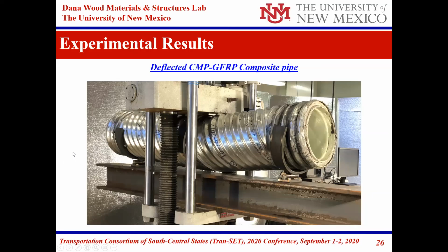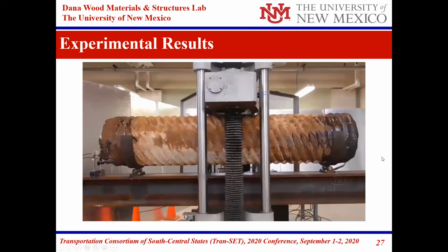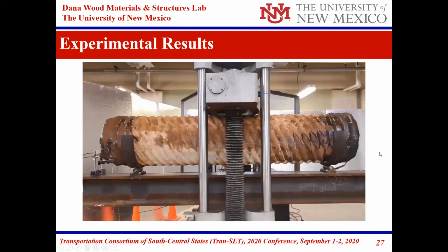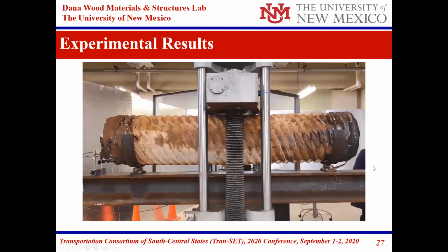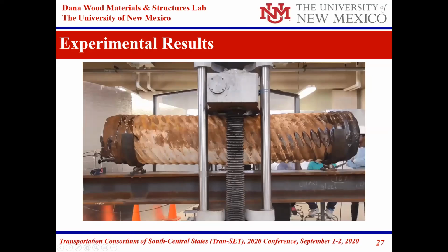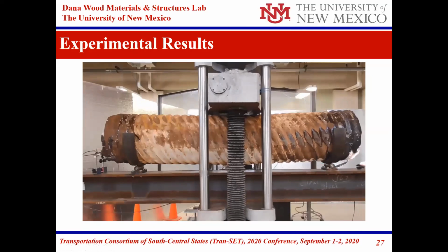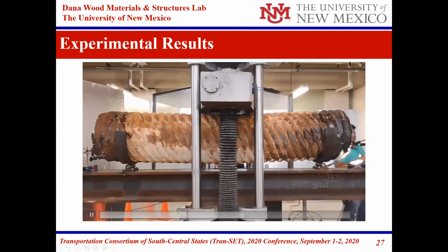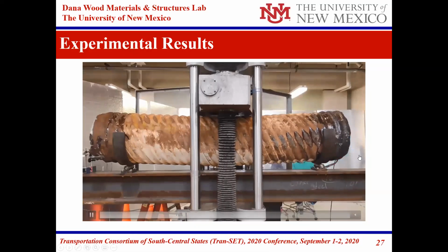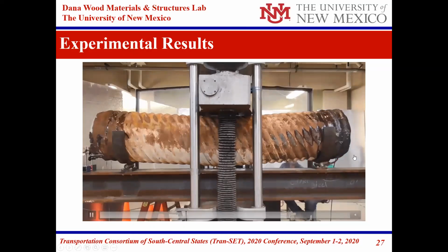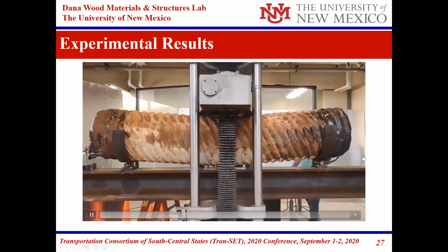That confirms that the GFRP can be bonded well to the pipe and can take the load. I repeated the test with the case of the corrugated metal pipe. And you can see again the test, another test that we did in about 7 hours. And the pipe again at the end, large deformation, similar to the case without the corrosion, and failure very similar to the case without the corrosion.